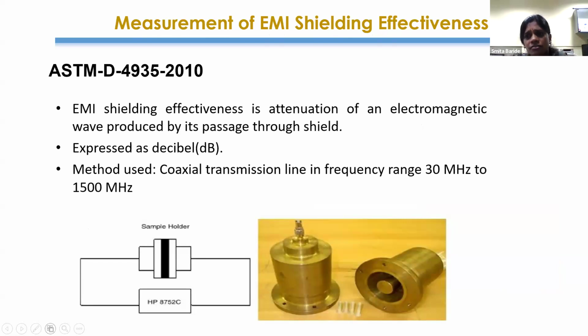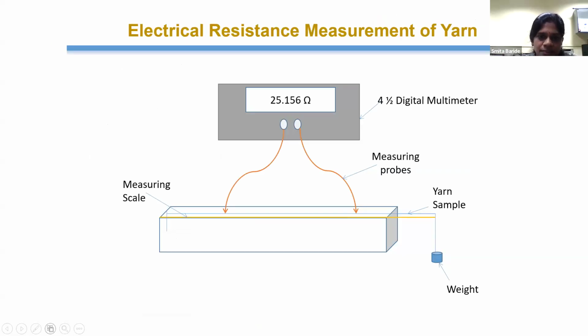The more the conductivity, the more shielding effectiveness we will get. And as per this standard, we are able to measure the shielding performance in the frequency range of 30 megahertz to 1.5 gigahertz. This covers the EMI signals generated from mobile phones, microwaves and radio waves. So in BTRA, we can measure the shielding performance, and for our fabric or synthesized sample also, we have performed this test.